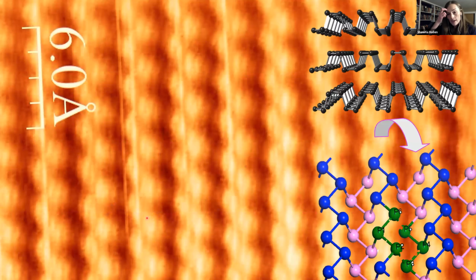Okay, so on that note, this is another material we've looked at. This material is called black phosphorus. If we were to look at the crystal in 3 dimensions, it has this sort of corrugated cardboard appearance with the layers that are separated by gaps. This image you're seeing is from the top of this crystal. So you flip this crystal over and you see there are these zigzags here. There are these zigzag rows of atoms on the top. So that's what we're imaging here, are the zigzag rows of atoms on the top of this black phosphorus material.